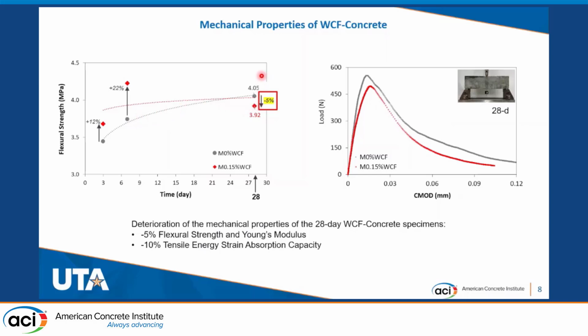However, we see that the strength of the 28-day specimen is reduced by 5%. And as can be clearly seen from the load CMOD curves, the load to crack mouth opening displacement curves shown in the graph on the right part of the slide, the 28-day waste cellulose fiber concrete exhibits a decreased load bearing capacity at both the elastic and the post-elastic stages of the deformation. That results in a reduced overall tensile energy absorption capacity of the fiber composites by approximately 10%.